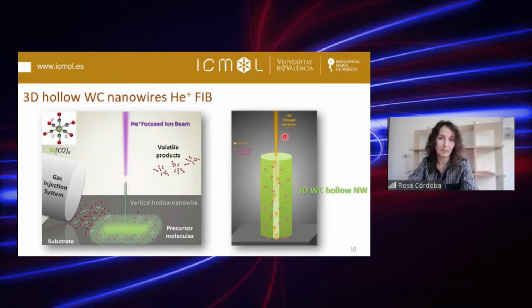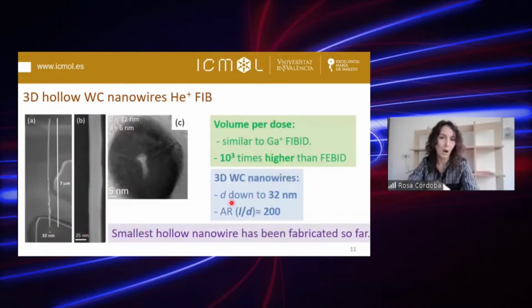So just by using this very simple strategy, I was able to draw hollow nanowires with diameters down to 32 nanometers in the outer diameter and 6 nanometers in inner diameter. And the aspect ratio of these structures was around 200. You can see here the length is around 7 microns, and this is something that is very difficult to obtain using other nanolithography techniques.